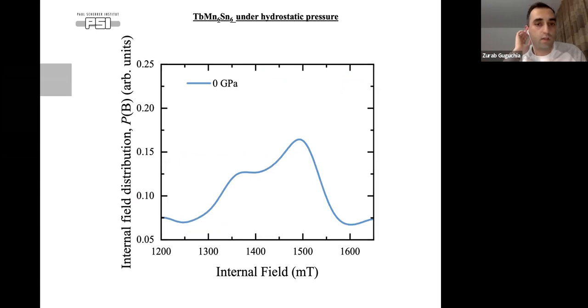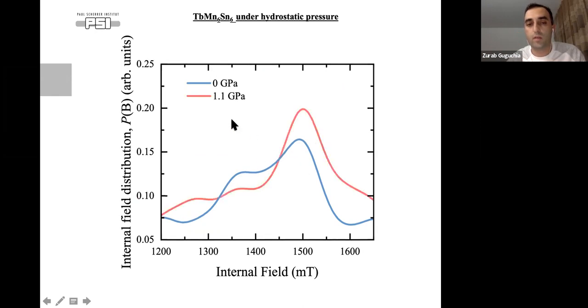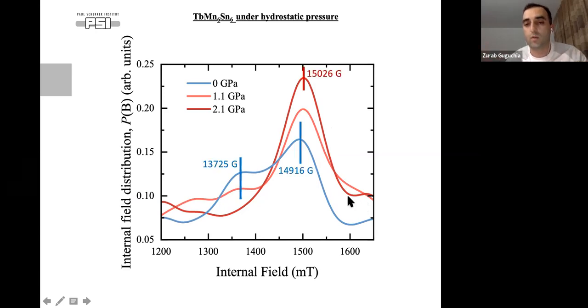So then what we did, we tried to tune the system with the pressure. And you see that at zero pressure, we have these two frequencies, as I've shown you. This is the more dynamic patches, and this is static. And then when you apply pressure, you promote this. So at 2.1 GPa, you have only the truly static C-axis aligned structure in 100% of the sample. So basically, with pressure, we can promote the, let's say, topologically active static state. And we can also increase the temperature by 5 Kelvin, not so much. But to see this nice interplay between these two states is quite exciting.